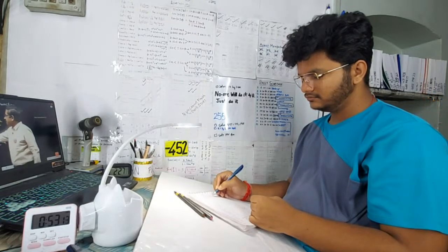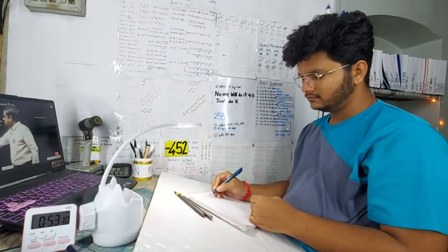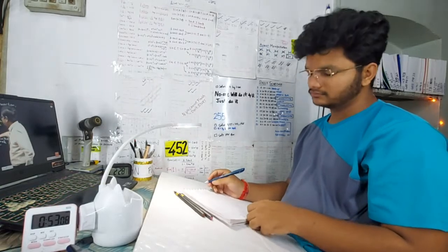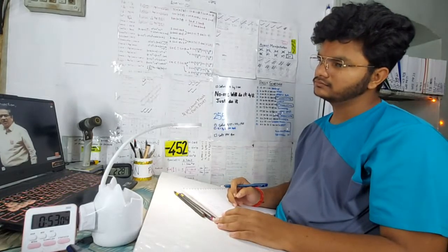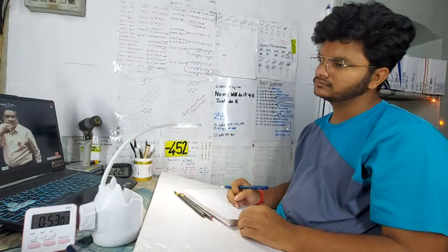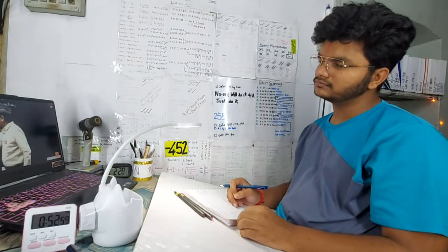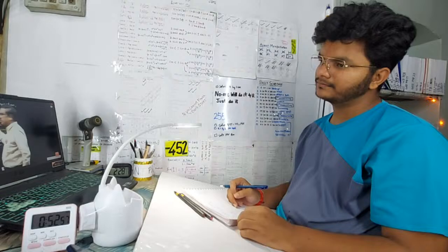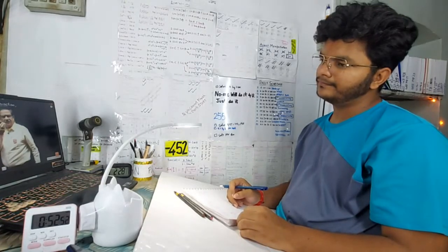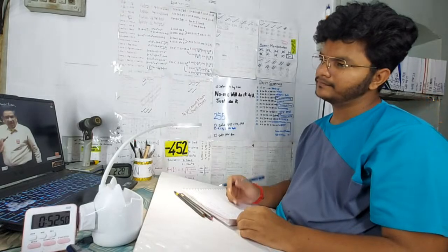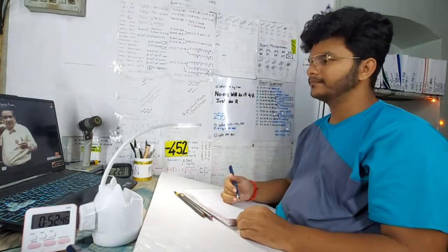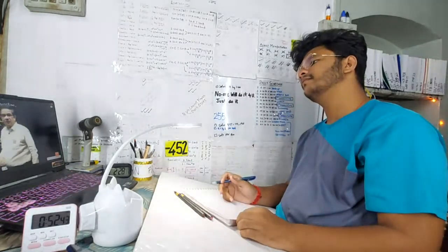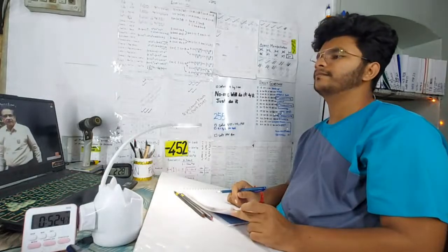Similarly, as temperature is increased, let us see what's going to happen. As temperature is increased, nucleation rate decreases. When nucleation rate decreases at higher and higher temperatures, only at a few locations will new phase pearlite form. But that small nucleation rate is associated with large growth rate at high temperatures. Therefore, though at a fewer number of places pearlitic transformation starts, the portion which is transformed into pearlite is associated with large growth rate. Therefore, it will grow bigger and bigger in size.